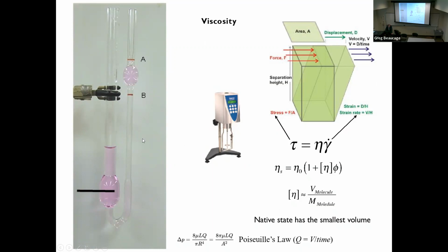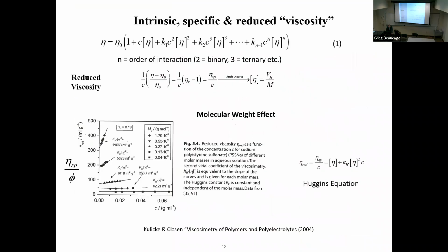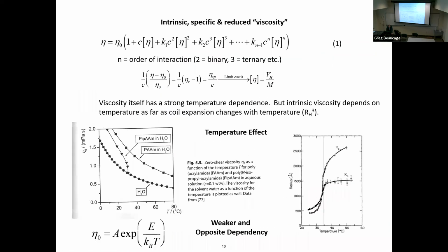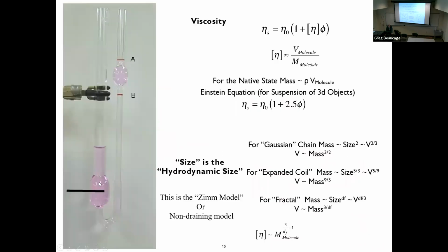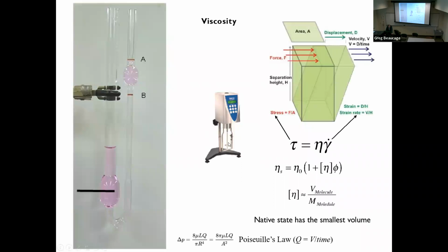The viscosity is also going to be exponentially temperature dependent. I have that in here somewhere. Oh, that was it right there. So you're going to have this kind of temperature dependence, and you need to control the temperature carefully, because the viscosity changes a lot with temperature. The Couette viscometer is usually got temperature control in it. The cup is insulated, and it's got water that runs through it. So you get isothermal, and you can ramp temperature and get the activation energy for viscosity, like the exponential argument. It gives you the energy it takes an atom to flop over another atom.